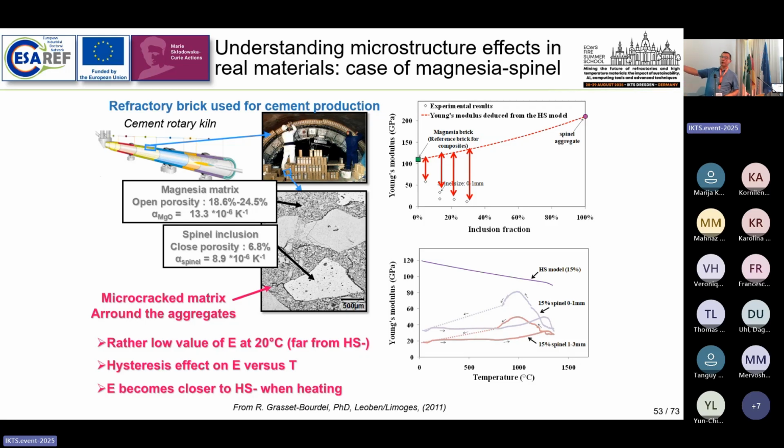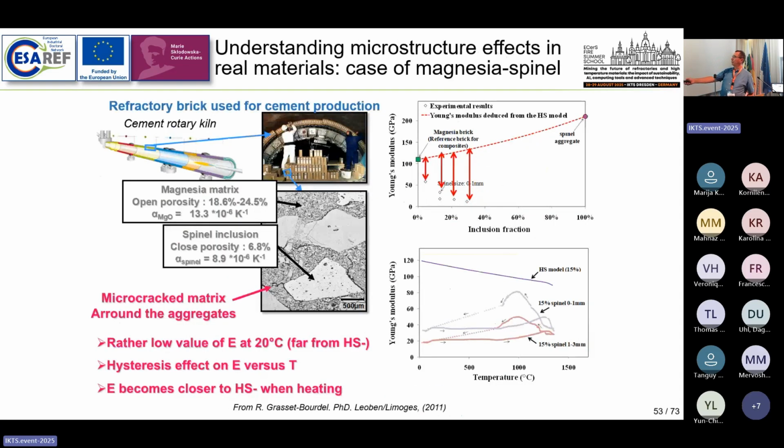So in that way, you can have a quantification of the damage if you know exactly where you should be without any crack. And if you do the measurement with crack, then you are able to make some quantification in a precise way. Of course, if you heat the system, you have, again, a hysteresis curve. Of course, this is not so beautiful because you don't close the crack in a perfect way in that system in comparison to the previous one. Nevertheless, you still have a hysteresis curve which demonstrates that you have a closing mechanism.